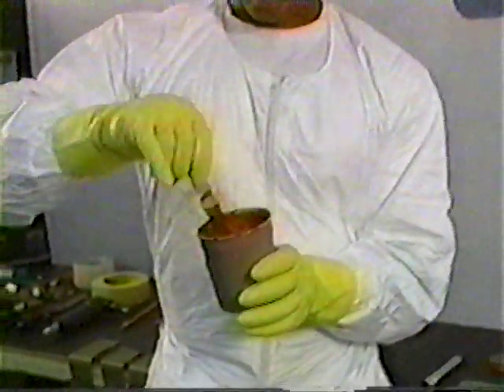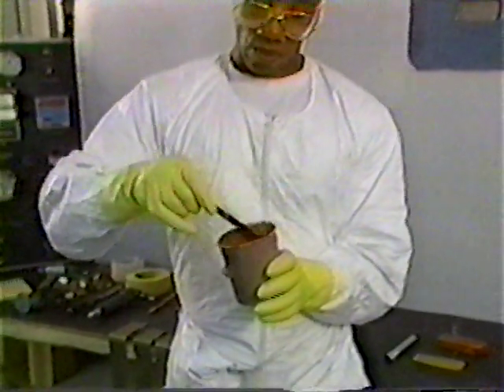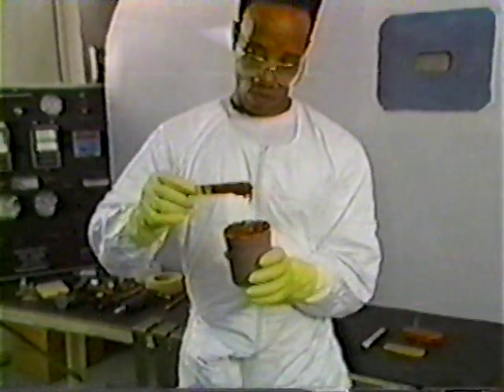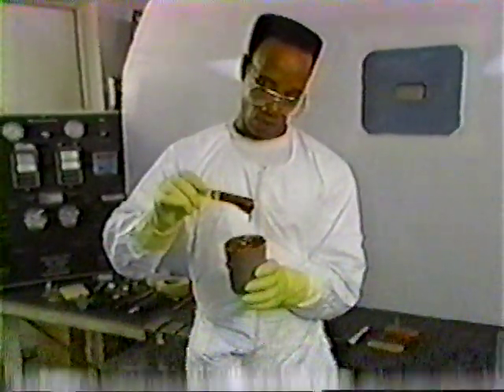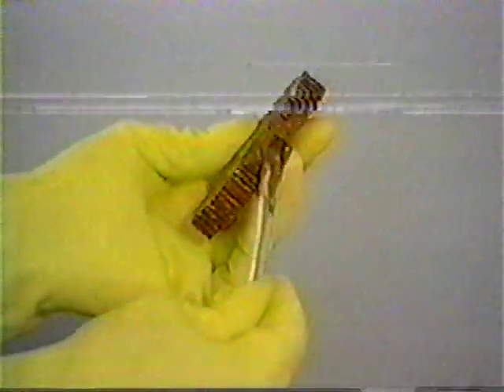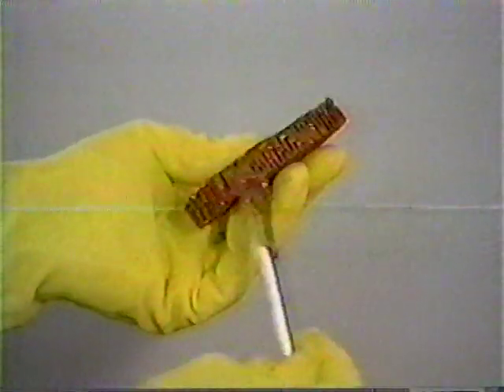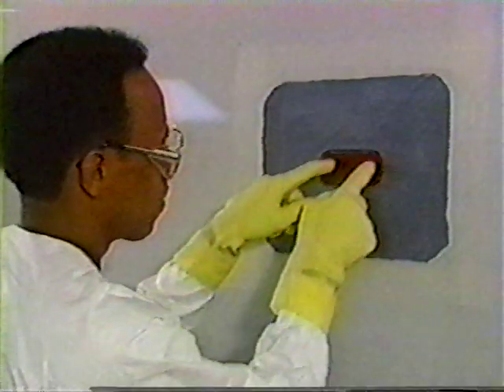Mix the appropriate adhesive materials, adding micro balloons to thicken the adhesive so that it will not run. Then, apply the mixture to the panel and the edges of the honeycomb core on the interior of the repair area, as well as to the sides and bottom of the core plug. When inserting the plug into the repair area, be certain the ribbon direction of the core plug matches the ribbon direction of the surrounding core.